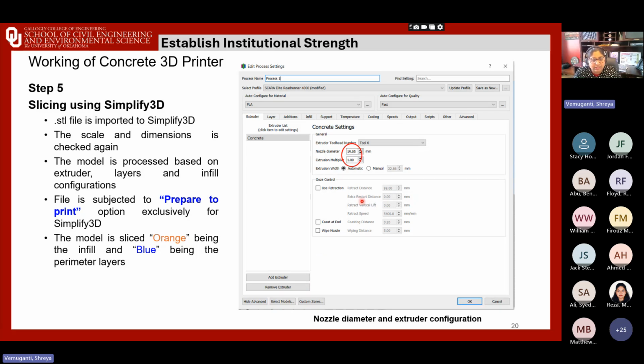If you look at specific parameters here, like nozzle diameter, we had a 19 millimeter nozzle diameter, which is obviously much larger than plastic printers, right? So we had to adjust those extrusion multipliers and control flow rate because these are critical parameters. If extrusion is too low, we get weak, porous layers. If it's too high, then the layers may actually collapse. They might lose shape. So it's a bit of a learning curve. We learned a lot during this process.